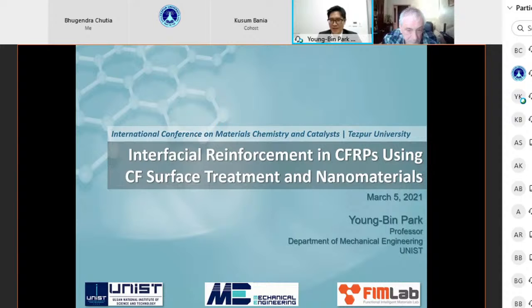I have two parts to present. The first topic has to do with reinforcing the interface between carbon fibers and nylon PA6-based matrix by incorporating carbon nanotube modified silane. Silane here serves as a coupling agent between the fiber and the matrix. Also, in addition, we are trying to promote mechanical interlocking by directly grafting or growing zinc oxide nanorods on the surface of carbon fibers. So this is a multifaceted approach for enhancing the interfacial bonding within a carbon fiber composite.